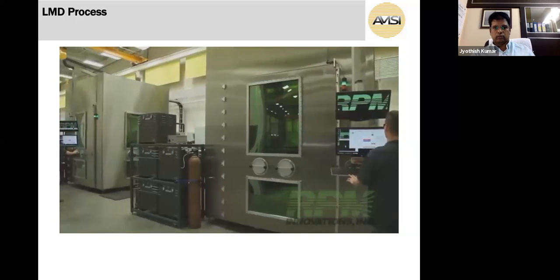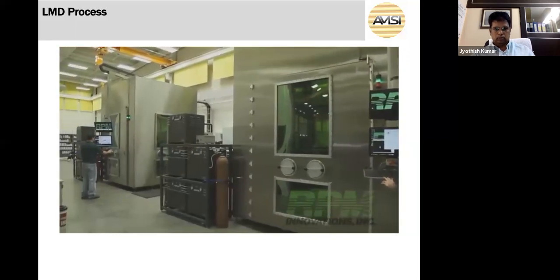Once the chamber is prepared, the build can begin. The laser fires and creates a melt pool on the surface of the target plate. A stream of powdered metal is delivered into the melt pool. When the powdered metal impacts the melt pool, it is absorbed into the melt pool and creates a weld bead. Fusing multiple layers together generates a 3D solid metallic build.